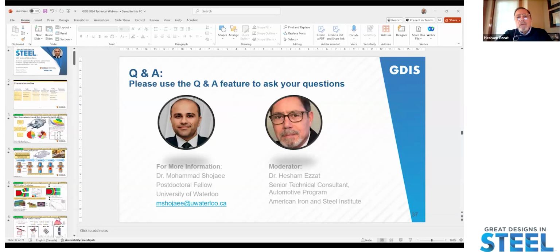Okay, let me move on to another question. Have you considered single weld with 3 or 4 sheet stack-ups? Or is that still too early? We have some projects that we're working on multi-stack-up geometries. It gets a lot more complicated in those cases, especially with stack-ups of different strengths and different thicknesses of the sheets, where the penetration of the fusion zone in different sheets is not equal. So you really have to manipulate the welding schedule quite a bit to get a good nugget in multi-stack-up geometries. That's a huge challenge that we're working on in our lab.